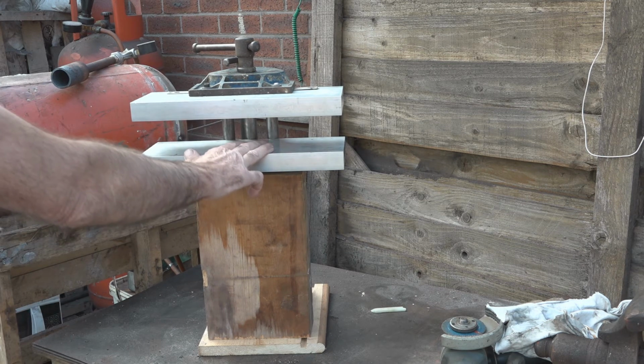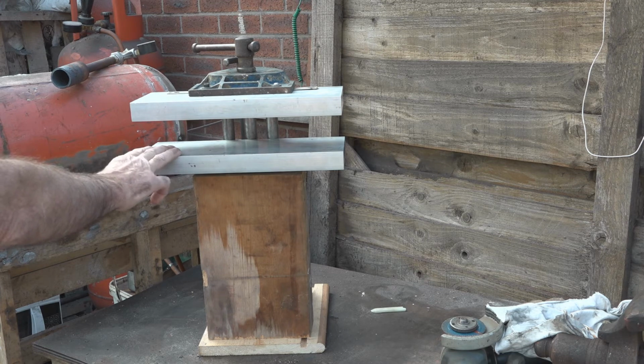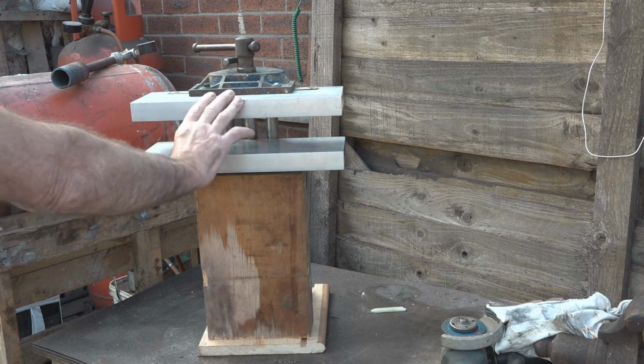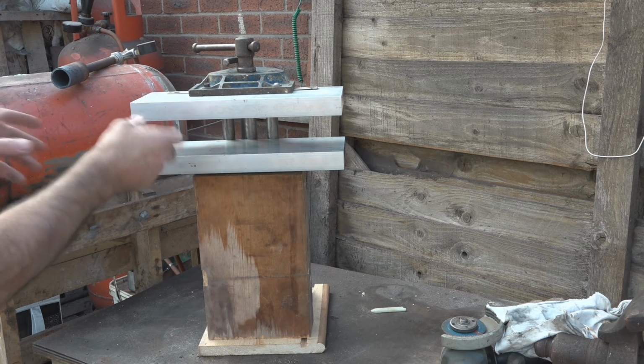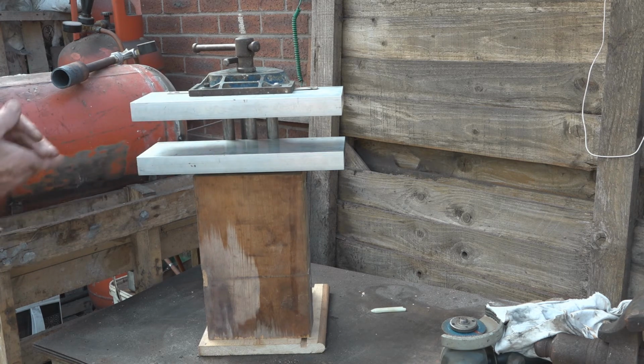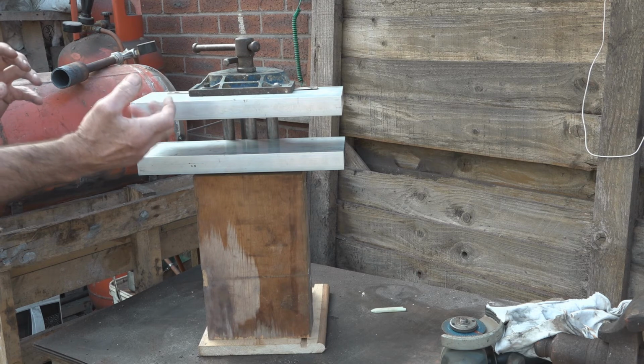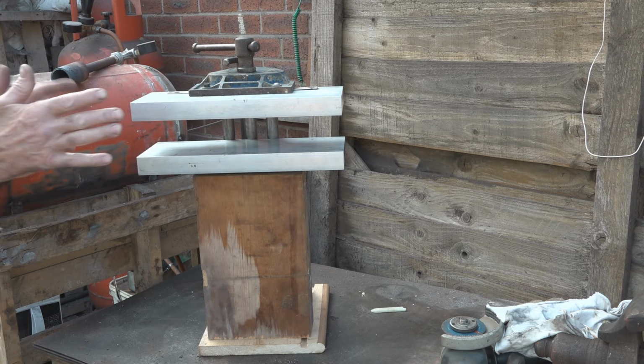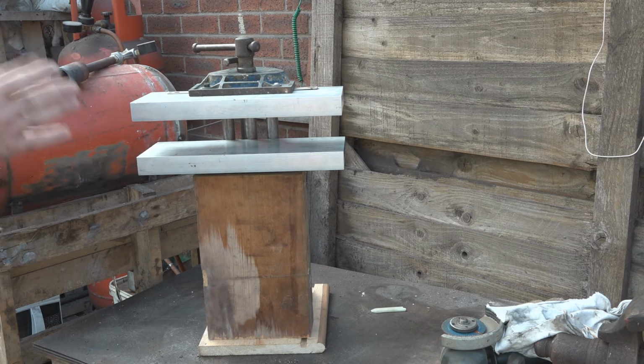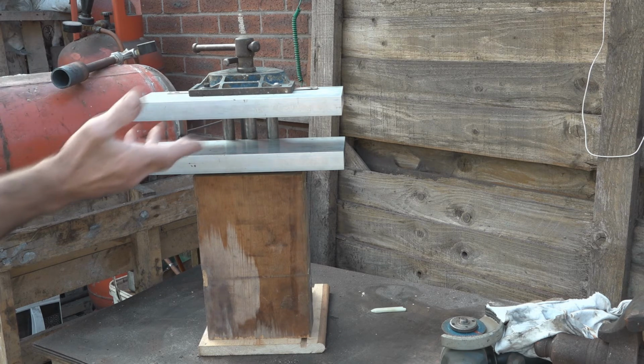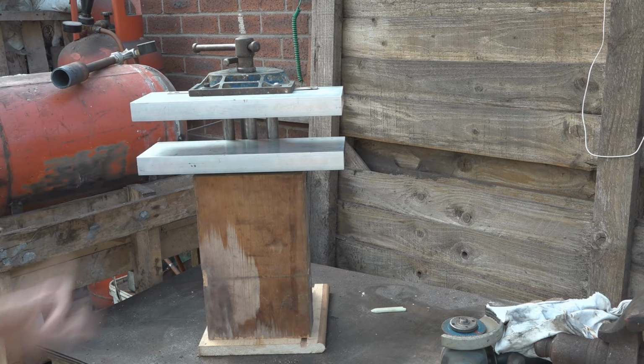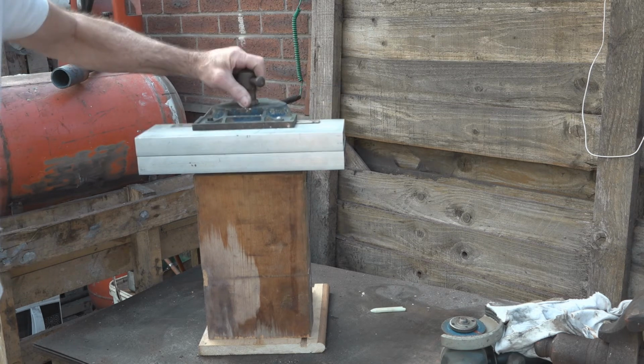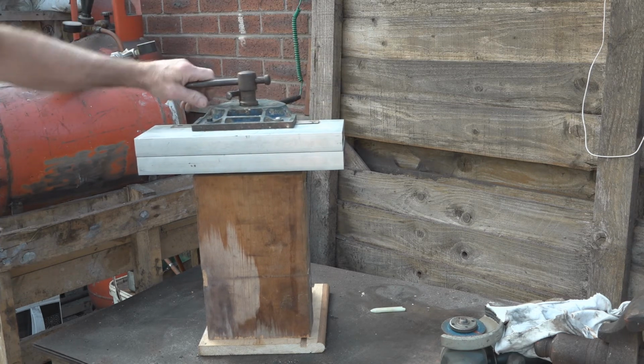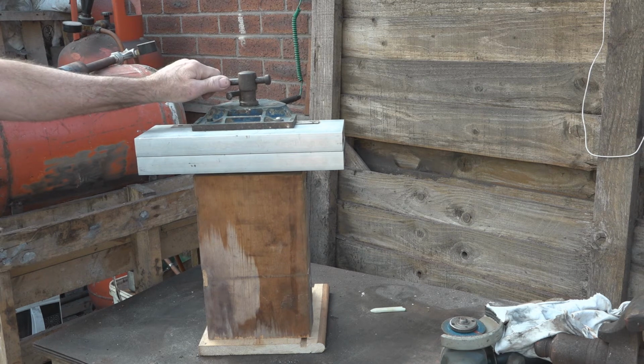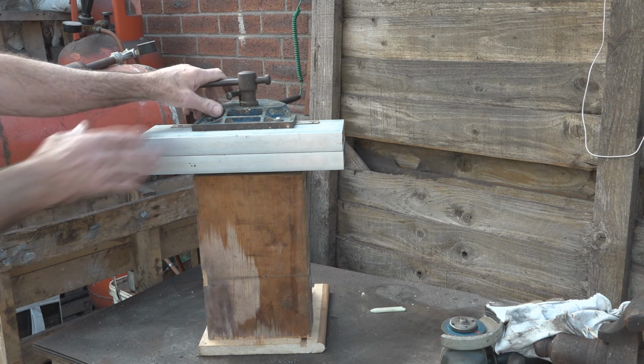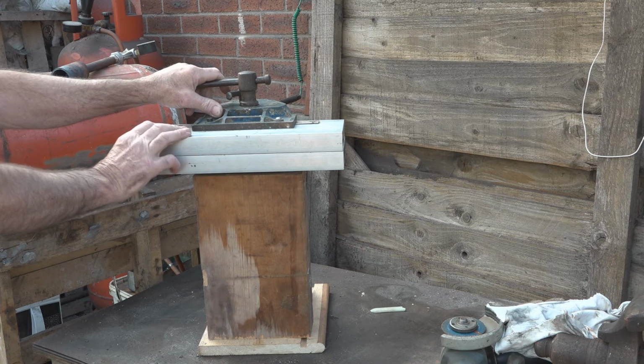The stainless knives, the D2 knives, are brought up to temperature, and they're actually quenched between these plates because they're in a stainless steel packet. It heated up inside a stainless steel packet, which keeps the oxygen off the steel, and it stops the edge, it stops the faces getting full of scale and decarb. So they're brought out in the packet and then literally just dropped in there, tightened up, and I'll leave them in there for about 2 minutes, and it does a great job of ripping the heat off the steel.